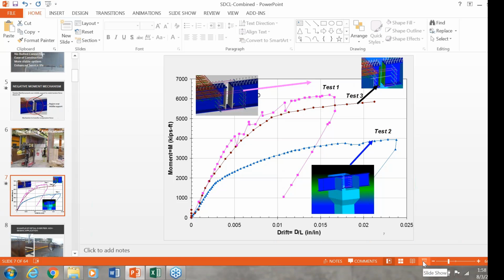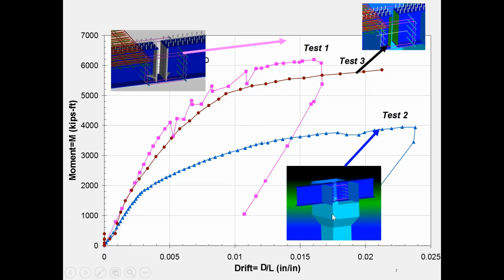Okay, so on the lower right-hand detail, which, yes, that one right there, where we didn't have the bearing plates, you had indicated that there was concrete crushing and it reduced the capacity by 50%. And then further on, with the bearing plate detail, you indicated that a gap was acceptable, maybe up to 1 inch between the end bearing plates. And it seemed kind of counterintuitive. If the idea was to prevent concrete crushing and you're allowing a 1 inch gap between the bearing plates, would that crushing still occur, or should there actually be some kind of contact area between the two bearing plates?